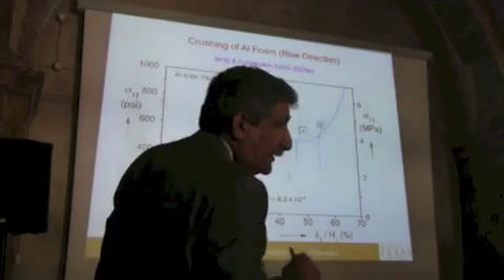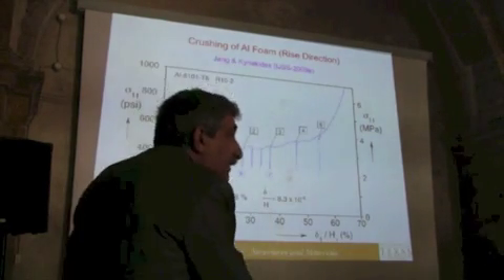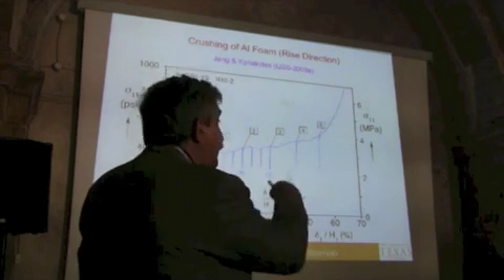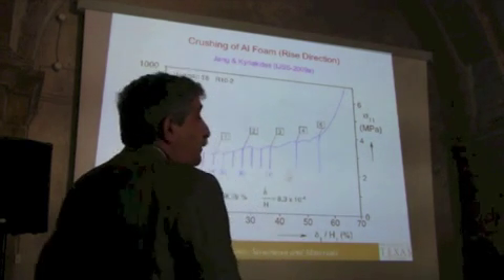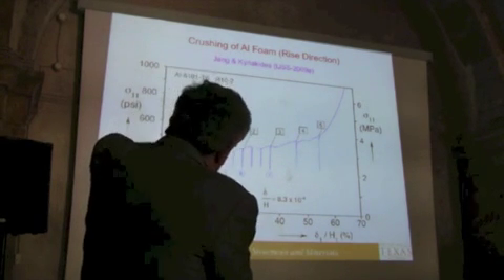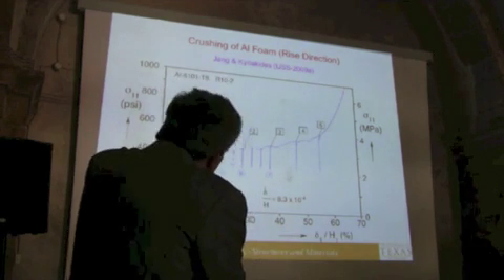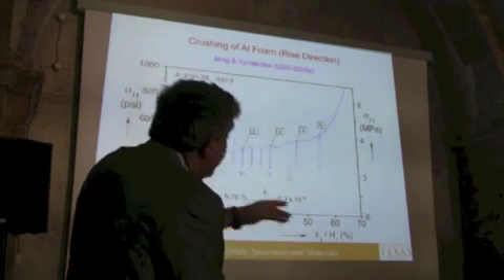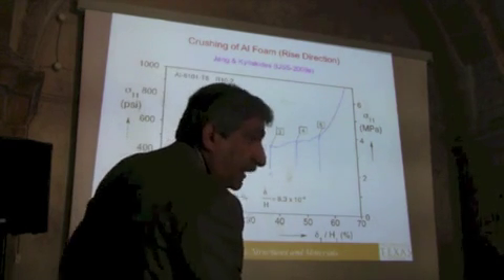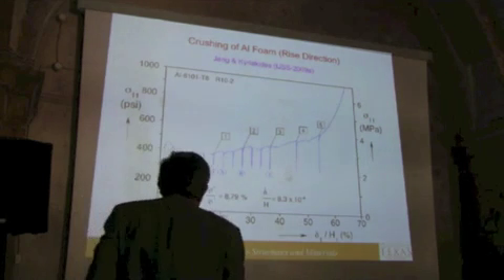We have a poor man's, a small X-ray tomography that is tabletop, and we could not do the experiment in situ. So what we did is we loaded it. This is an elastoplastic material, so you load it and you reach a certain deformation. We unloaded and then took a scan. So this is an experiment that took 2 weeks actually, because the scan for us was 24 hours.